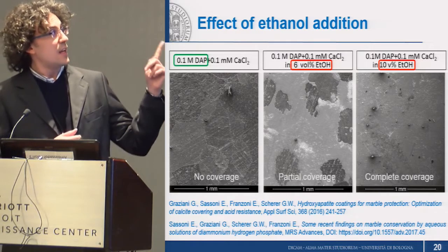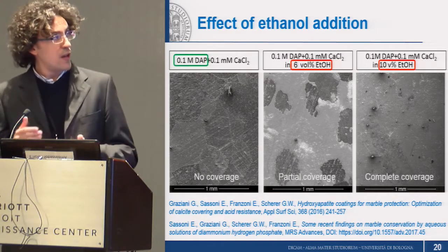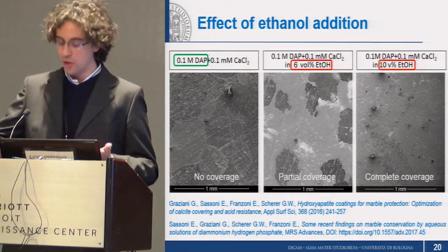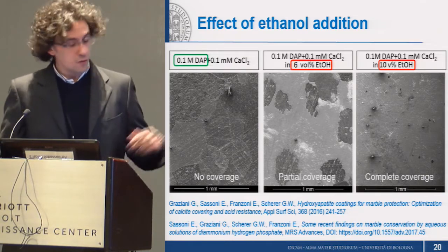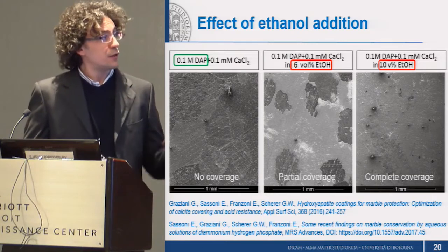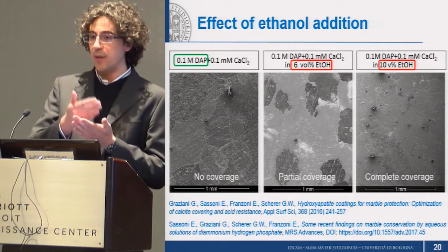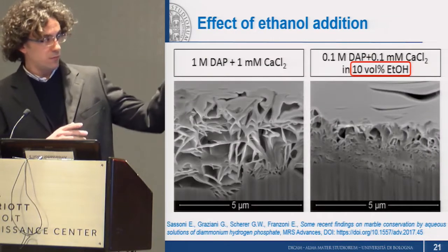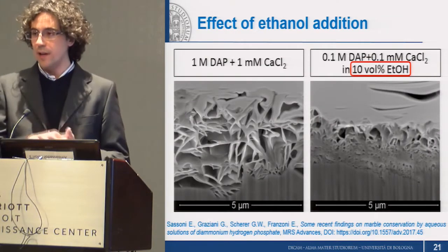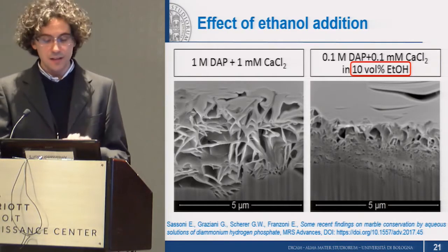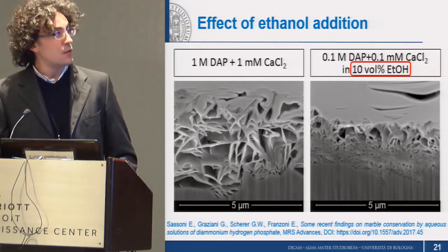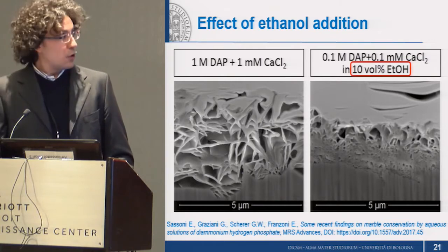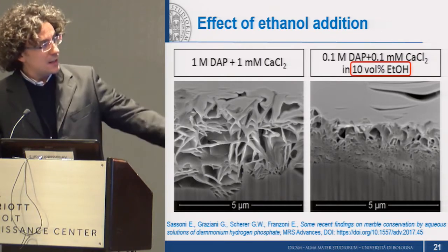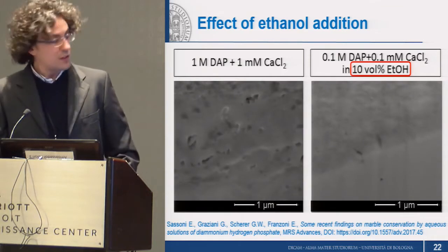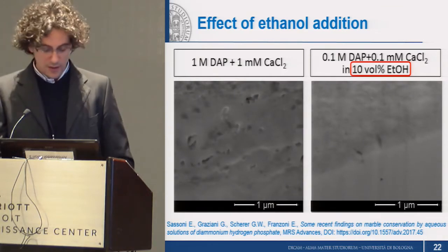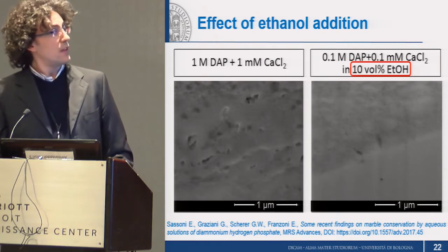So as you can see, at the same very low DAP concentration, by increasing ethanol concentration, we were able to obtain a continuous coating. And also in terms of the coating microstructure and density, we were able to get a thinner layer with a significantly better density by adding ethanol to the solution. And so as you can see also the interface between calcite in the bottom part and the new phosphate phase, the presence of pores is highly reduced, which is positive.